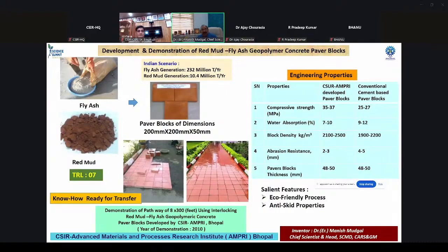We have also developed red mud fly ash based geopolymeric paving blocks. We developed around 5,000 paving blocks at AMPRI Bhopal and demonstrated them in the premises. The second picture shows the present status of these blocks. They are giving very good durability, and the unique property of this block is that it is an eco-friendly process with anti-skid properties. There is no algal growth on these blocks, so it has this unique property.